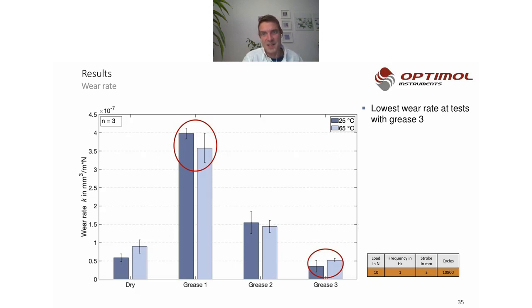But as you can see, this grease number 3 with its very smooth friction behavior will also be able to decrease the wear. And as you can see, there is a slight difference between low temperature and high temperature testing. So after we ran all those tests, we could come to our customer with this data and say: if you implement a grease, it would be very beneficial for your friction behavior, and that's good for the haptics for your customers while they use this mixer tap. But you should avoid greases number 1 and 2, because they are not so beneficial. Please move on with grease number 3.